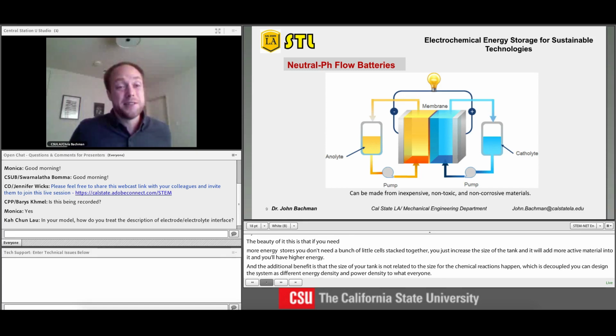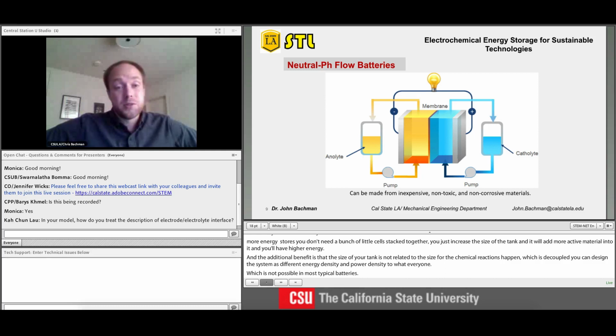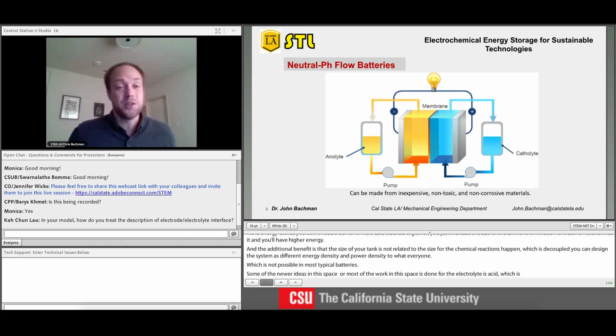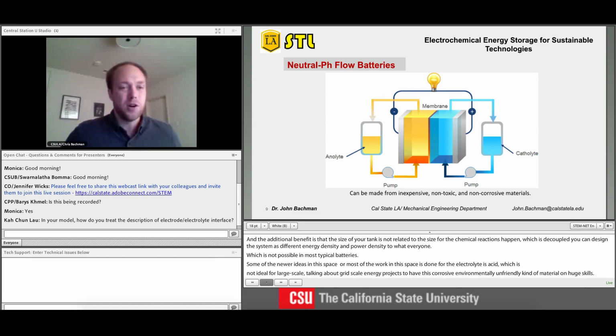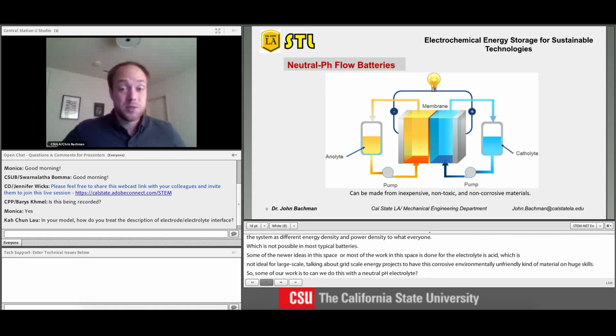So some of the newer ideas in this space: most of the work in this space is done where the electrolyte is an acid, which is not ideal for large scale. We're talking about grid scale energy projects to have this corrosive, environmentally unfriendly material at huge scales. So some of our work is, can we do this with a neutral pH electrolyte? Can we dissolve our active materials in something like water and salt, basically? One, it's much less expensive, and it's non-toxic, and it's non-corrosive.